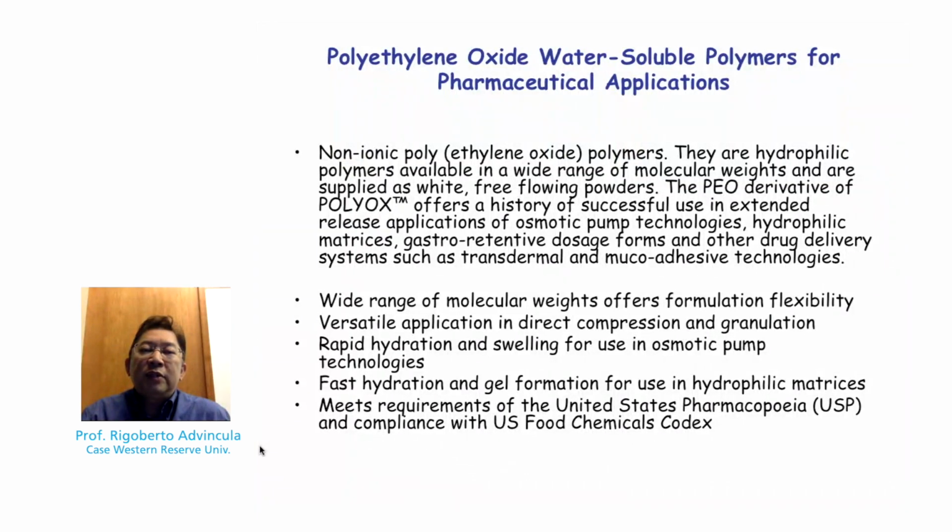Polyethylene oxide, of course, is a water-soluble polymer that is non-ionic, meaning it doesn't have any specific negative or positive charge that can interact with the DNA or polypeptide, and therefore PEO is in general a very useful polymer that can be used to improve drug efficacy or used as conjugates with proteins to improve their self-assembly.